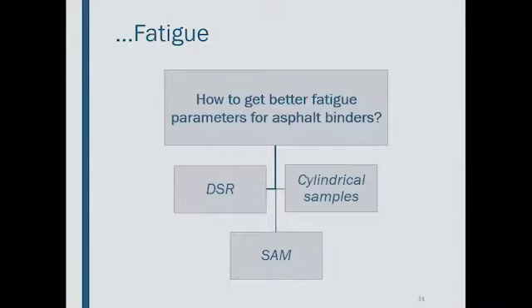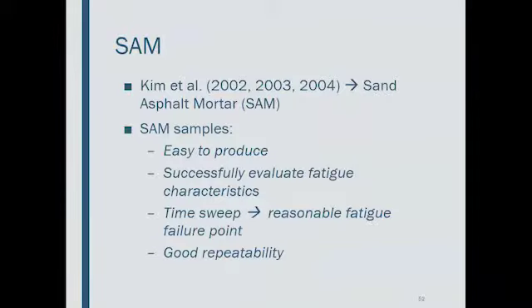Then we think about how to get better fatigue parameters for asphalt binders. And with this experience of the FAM, we are trying to use the rheometer and the cylindrical samples, but working with sand asphalt mortar. There are some papers that present results of these studies. These papers show that SAM samples are easy to produce and successfully evaluate fatigue characteristics. Time sweep tests presented a reasonable fatigue failure point with good repeatability.